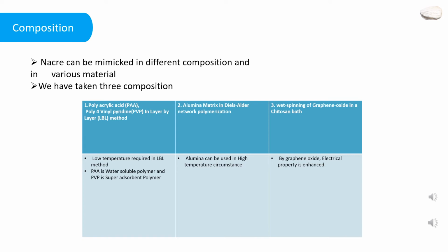In our second composition, the alumina matrix. Yes, aragonite is an unstable compound. When it is at a higher temperature, it changes to calcite. That means it will lose the nacre property. So, for higher temperature circumstances, this alumina matrix will be useful. Our third composition is with graphene oxide. The usage of graphene oxide tremendously increases the electrical property of the material, where the material achieves both mechanical and electrical property.